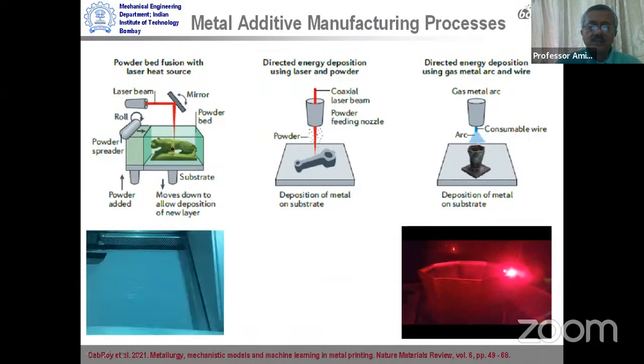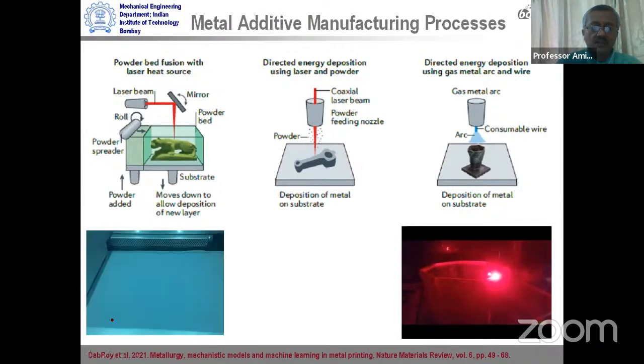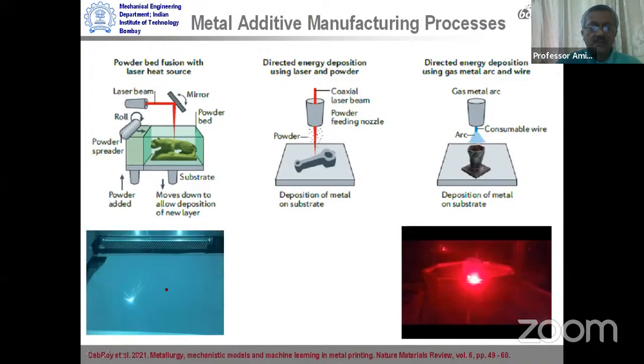Broadly, we classify this particular process as a powder bed process, where a bed of powder alloy is laid layer by layer, and the laser works on that to melt and solidify selected areas to create a three-dimensional part, as we see here. In contrast, these two are directed energy deposition processes. I really don't know why the name has come to be directed energy deposition. Perhaps the fact that the heat source and the feedstock material both come together and are directed to a local area to create a three-dimensional layer net shape is the genesis of the name of these processes, and especially of the group as directed energy deposition.